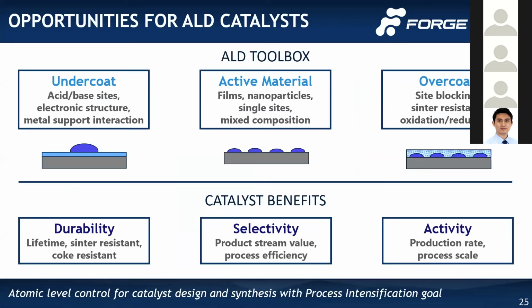In the ALD toolbox, this is what I was mentioning: we have overcoats, typically an oxide, but it could be some other material, maybe a mixed metal oxide, deposited on top of the catalyst that's made in a standard method, maybe incipient wetness. Or you have the active material deposition—you can use ALD to deposit platinum, palladium, rhodium, ruthenium, cobalt. Or you have undercoats, depositing an ALD layer, maybe a mixed metal oxide or an oxide, onto the base support, and then use a standard method like incipient wetness to deposit your active material, or use a combination of ALD methods to build your catalyst from the bottom up, which I'll also point out.